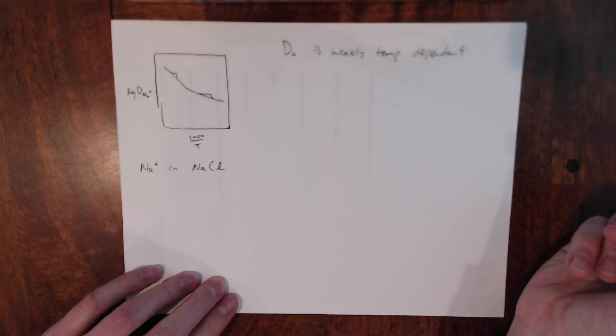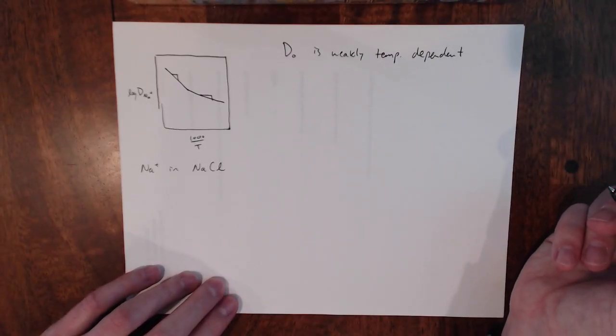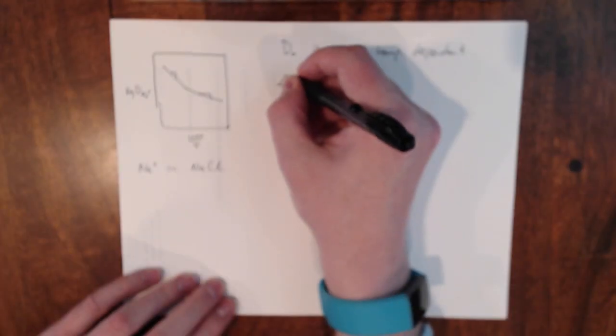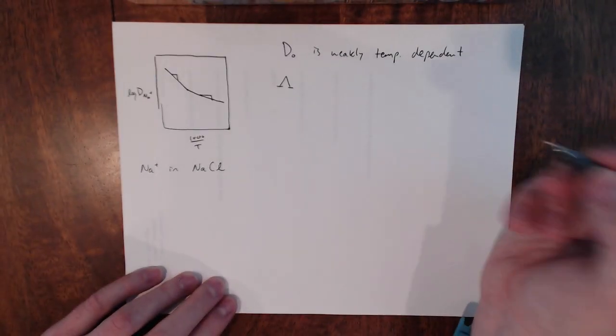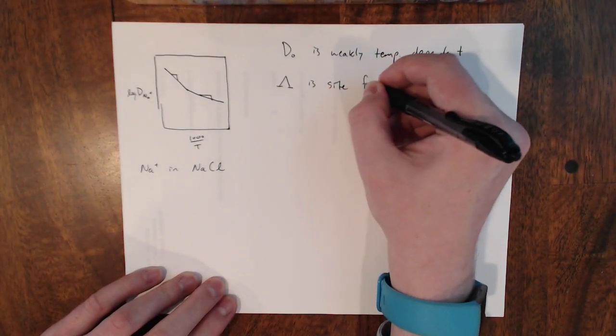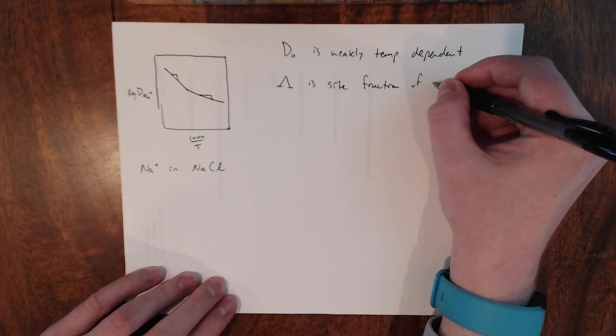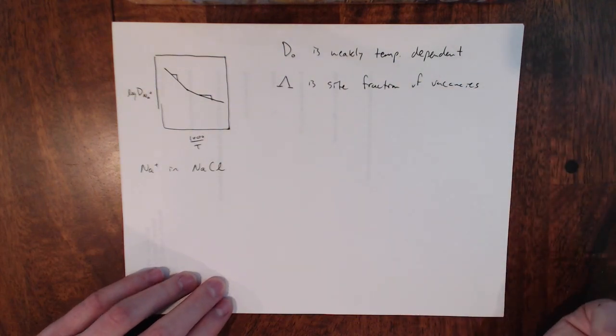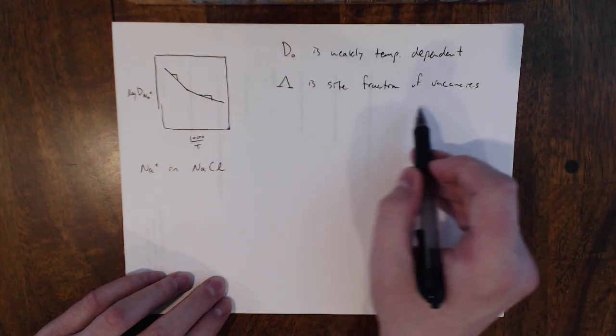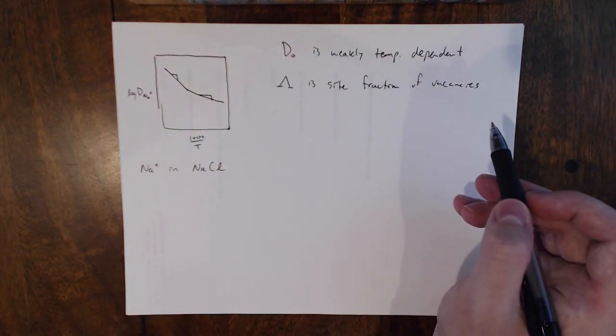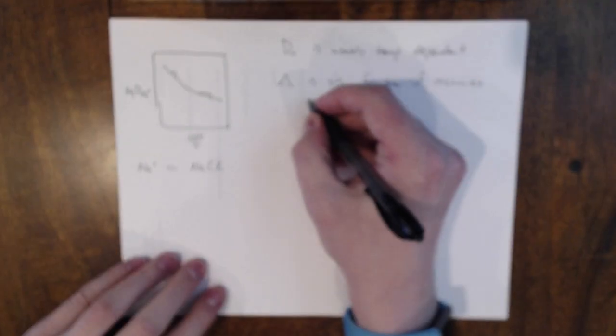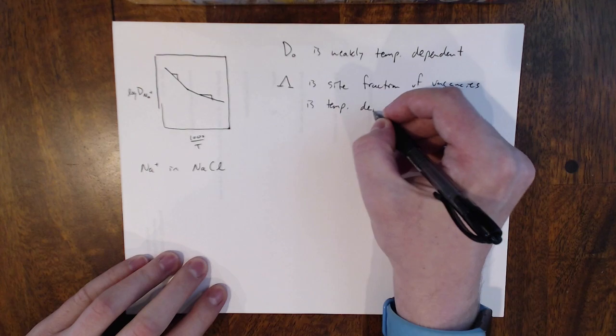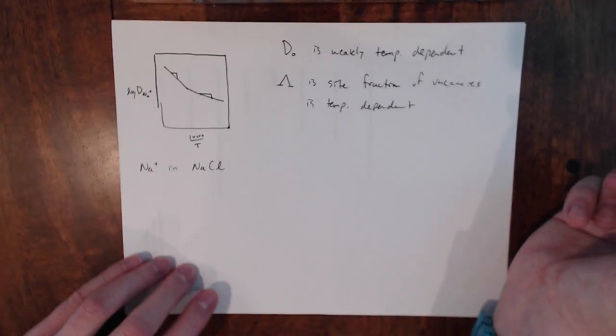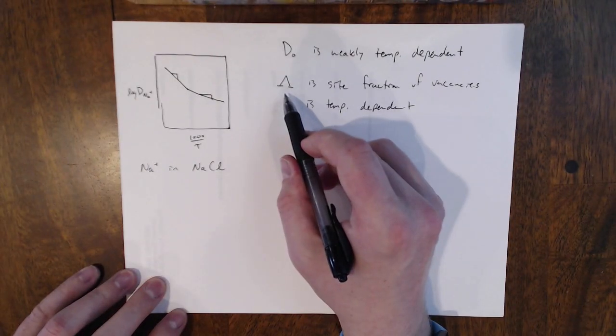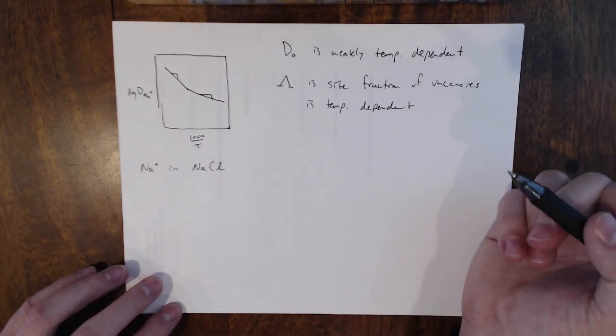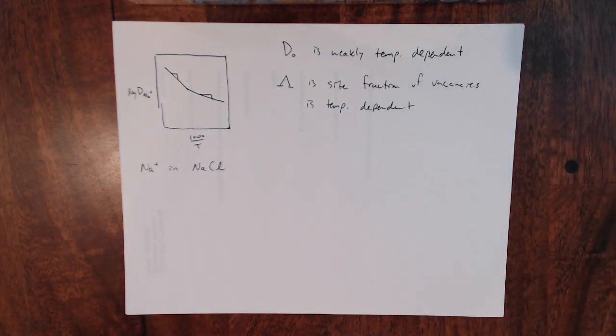All right, so that's going to be important here. Also, I mentioned this site fraction of vacancies, right? This is the site fraction of vacancies. So these appeared in the diffusivity equation. So the site fraction of vacancies, that is also temperature dependent, right? So that D naught expression, which has this term, is therefore temperature dependent. But again, it's somewhat weakly dependent. That doesn't mean it doesn't affect our results.